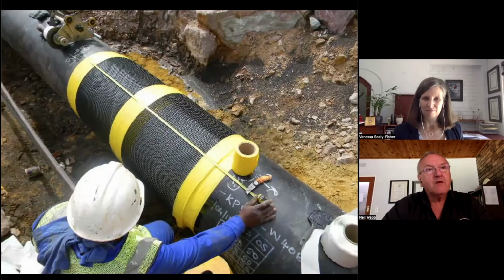However, going back to the question of mechanical strength, the tape here is an example of the tape being used on a 3-layer polyethylene coated pipe. So there's now a huge difference in the mechanical damage resistance of the two systems, albeit they both have the same electrical and cathodic disbonding properties. And in order to overcome that, you've got two options. You can either import sand for every field joint. That's not something that construction contractors like the concept of.